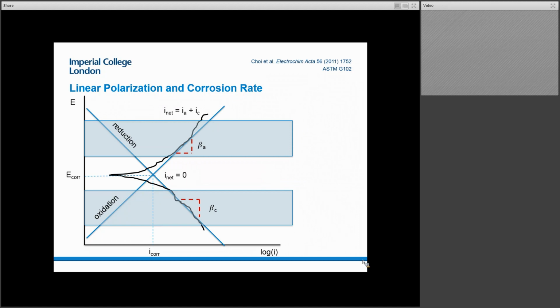So what's happening in that black, somewhat noisy example, which I've drawn, is actually the current response, right? And the current response is a net response. It's the combination of the anodic and the cathodic. But there's a point at which, as I introduced way back at the open circuit potential, that net becomes zero. But this is riding on a range of assumptions because if you remember, I talked about that, where we said that there was a single oxidation reaction and a single reduction reaction, and at which point those two become equal. We reach that point, right?